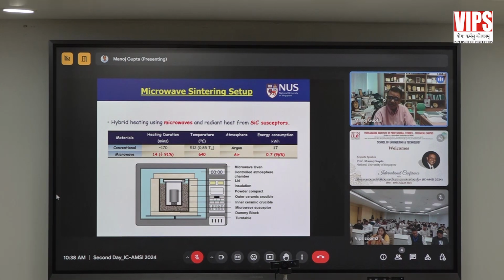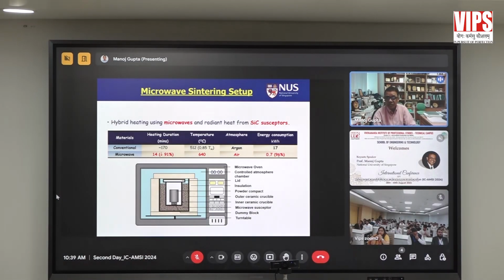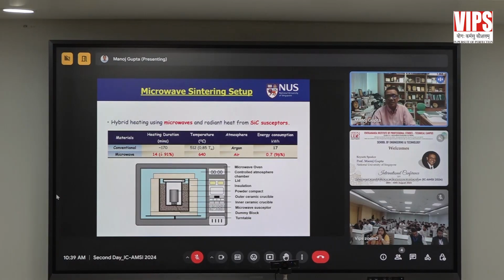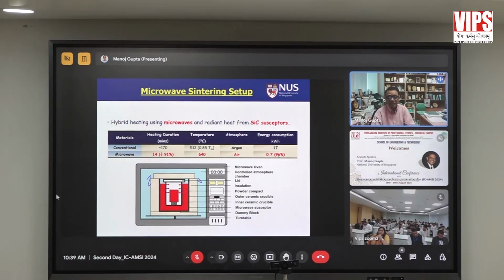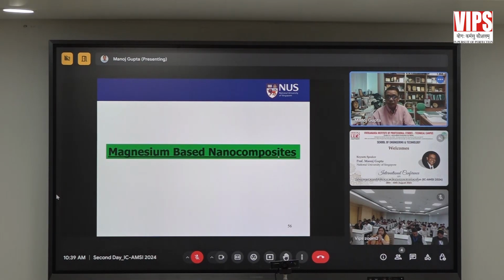Reduction in the energy consumption means my method is a green method, I'm using less energy. And the reduction in the heating duration and energy consumption makes my product cheaper than my competitors. So that is where sometimes you have to go to the newer technology to make your materials. And here, when you switch on the microwave, it heats the susceptor and it heats the billet, which also gets heated from inside out because it also absorbs microwaves directly.